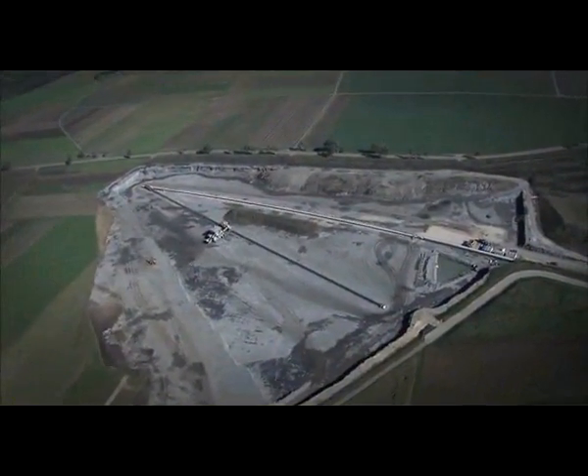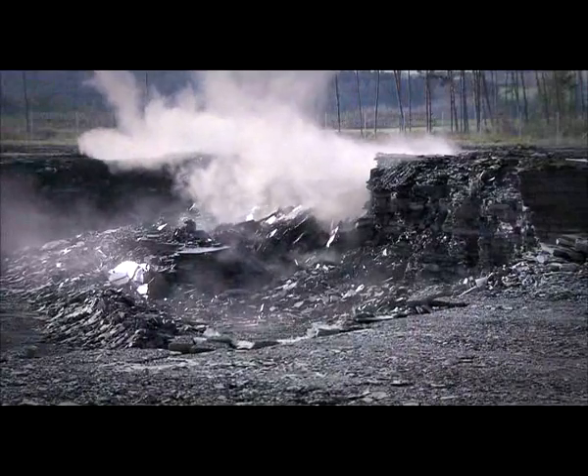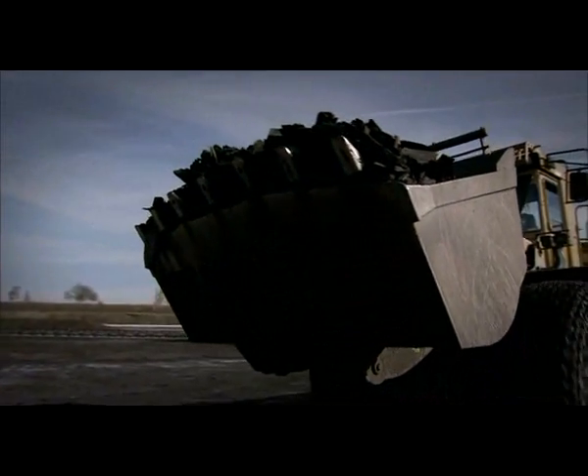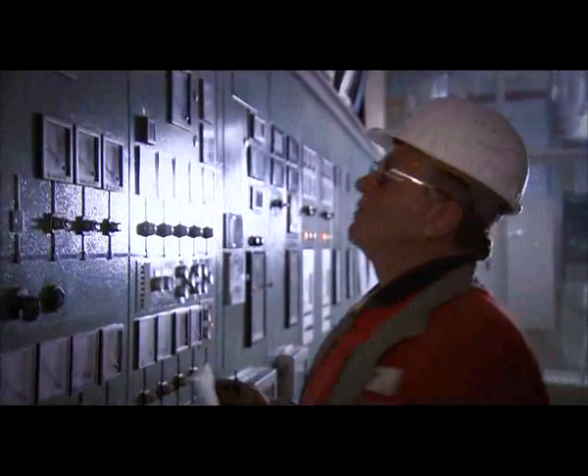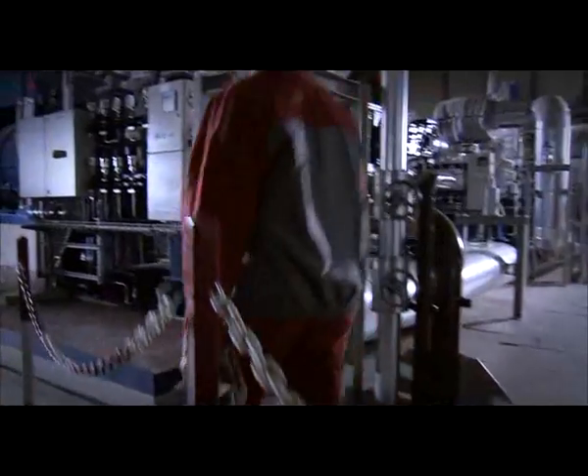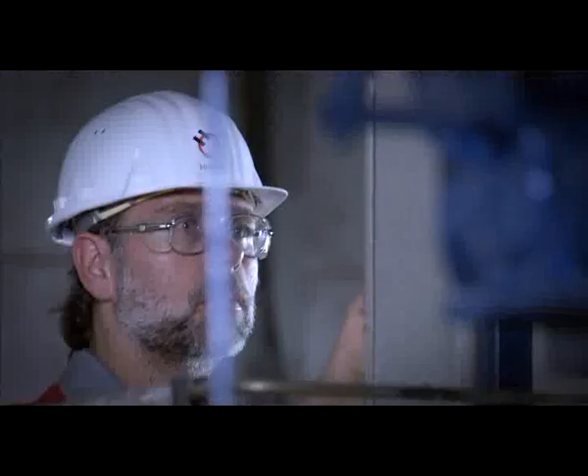We also have silo trucks for regional deliveries. Our Dotternhausen plant in southern Germany is unique in Central Europe because it uses oil shale as a raw material. The plant uses a combined process that logically exploits the shale's properties: mineral constituents make a high-grade clinker substitute, while the organic content goes to generate energy — a particularly economical method. The shale is burned in an on-site thermal processing plant that generates enough electricity to make the cement works entirely self-sufficient in power. Burned shale is then added to the cement as a substitute for clinker, resulting in a considerable reduction in CO2 emissions.